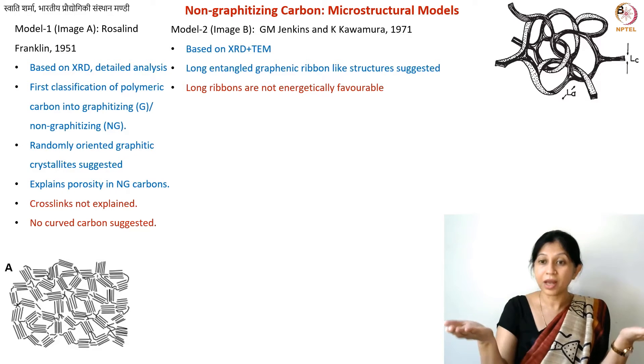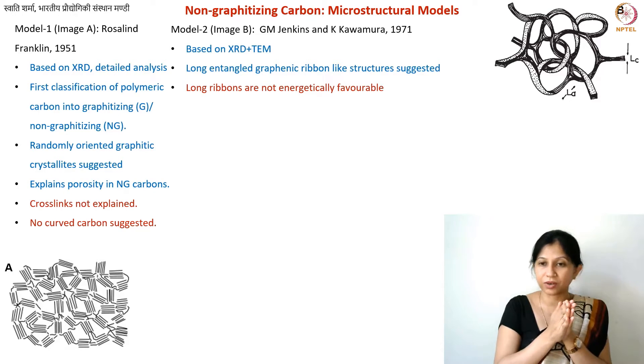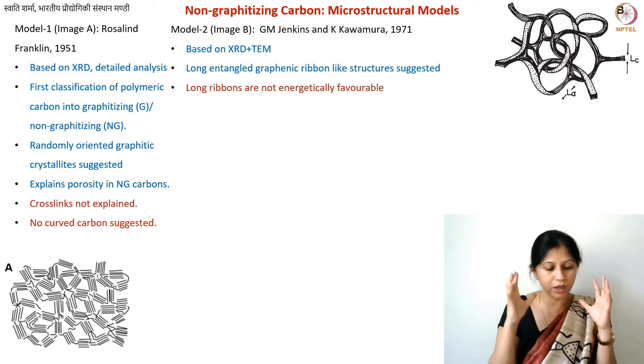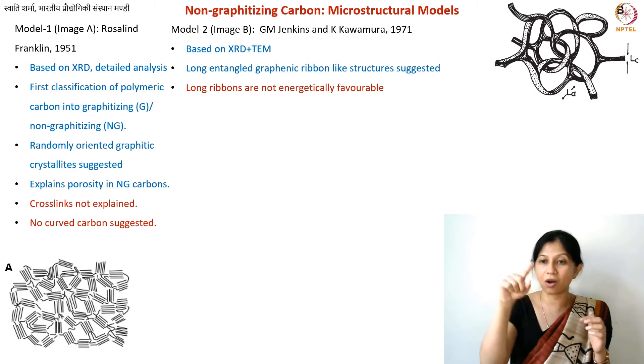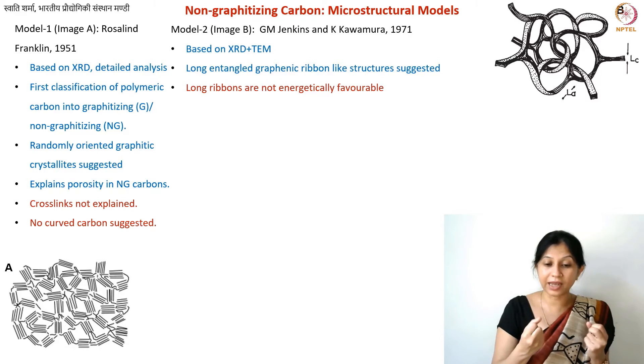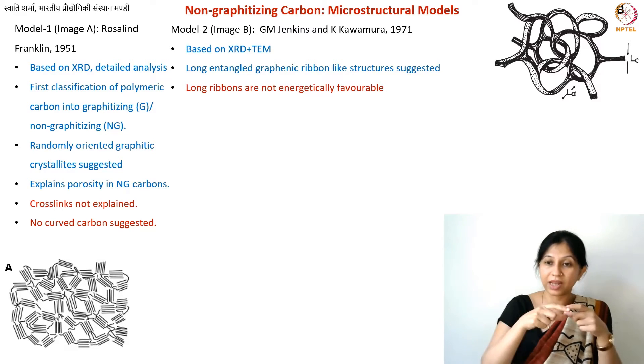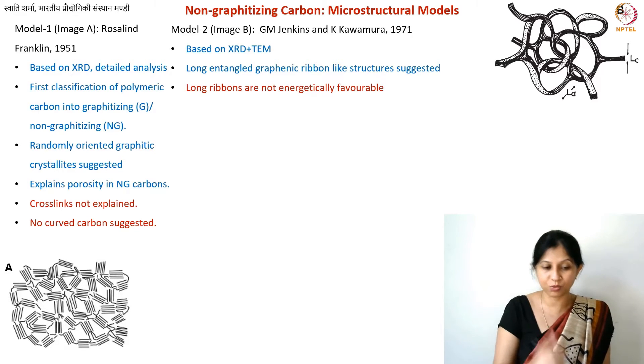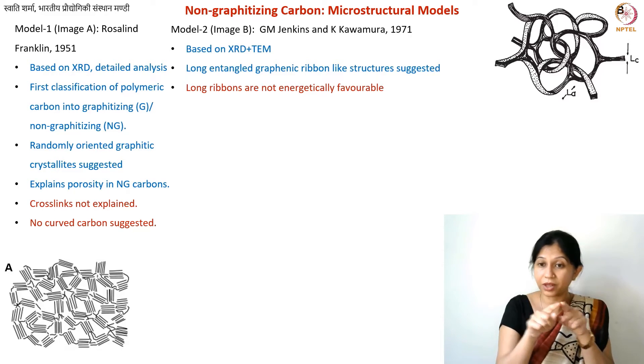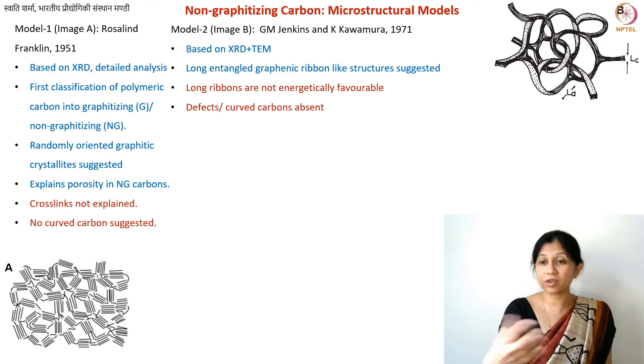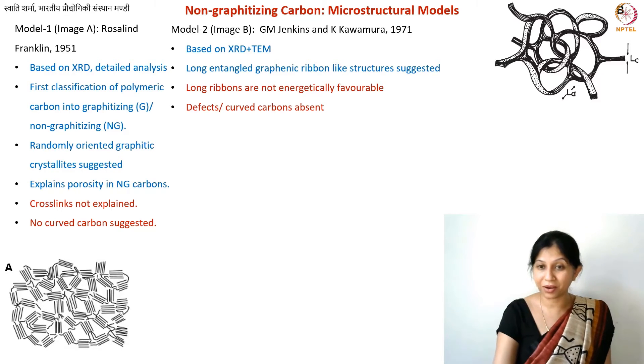In principle, your crystallites would not be symmetric. When you talk about La, the crystallite diameter, you are considering an equivalent sphere where the diameter should be the same in all directions. But if you have a ribbon-like structure, the length will be much more than the width — that is the definition of a ribbon. Whether to take La only along the length or also along the width of the ribbon was not very clear in this model.